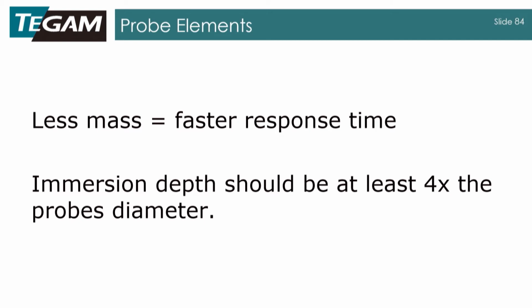And that's how we were able to see that if I were moving it up and down, you would have noticed that when it reached that temperature, it would have started fluctuating. And I know this from personal experience. So it is important to get at least 4 times the probe's diameter, or it's going to see that outside air, and it's going to start to affect your measurement.